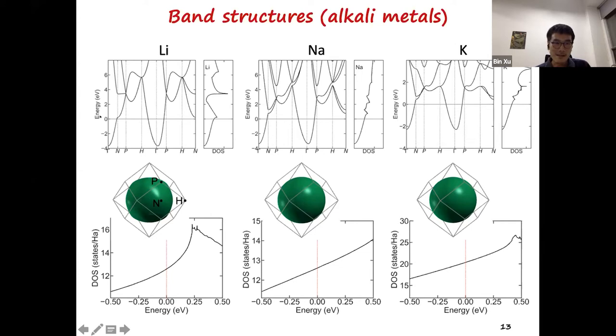If we look at the density of states for lithium, there's a strong increase versus energy near the Fermi level. So this is a strong deviation from the parabolic band behavior, or nearly free electron behavior. But for sodium and potassium, it is close to linear and is more free electron-like.